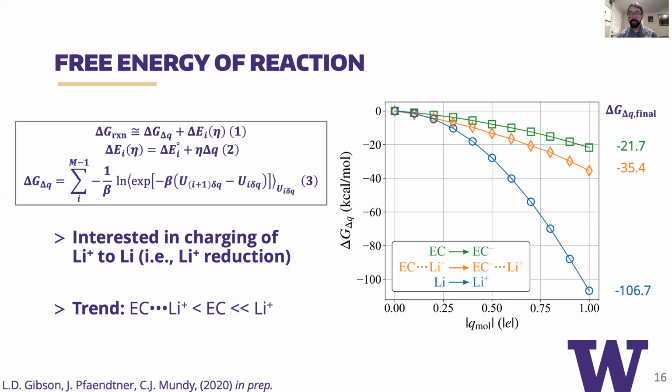Lastly, we have the free energy of reaction, which is a much more involved quantity to compute. And we see in equation 1 here that this free energy is comprised of two energies. The first is the change in the free energy of solvation, and the second is the change in intrinsic energy. Now, this intrinsic energy is defined below in equation 2, where we have this delta E naught, which is just